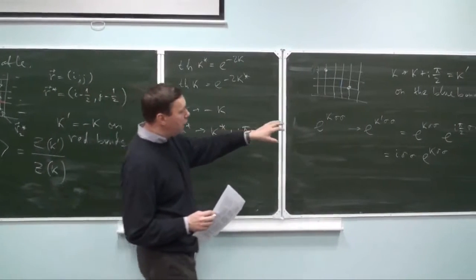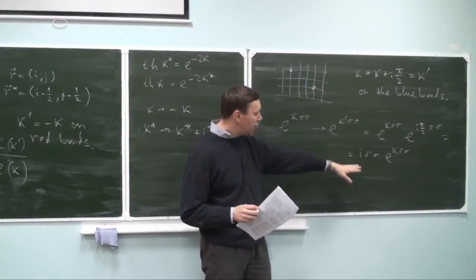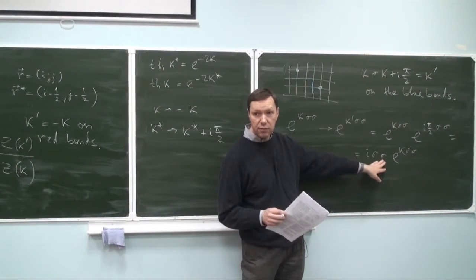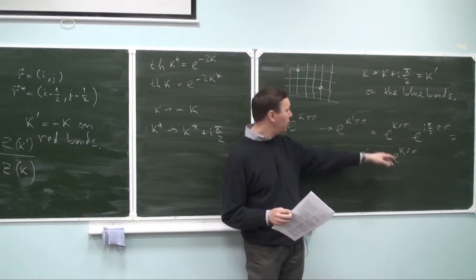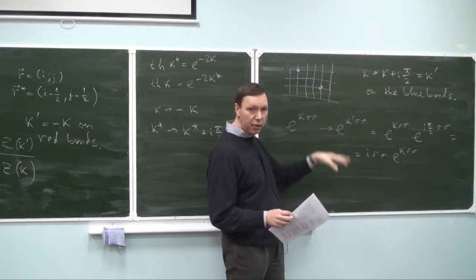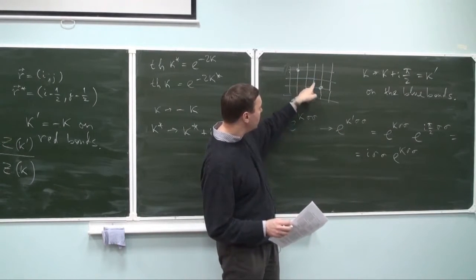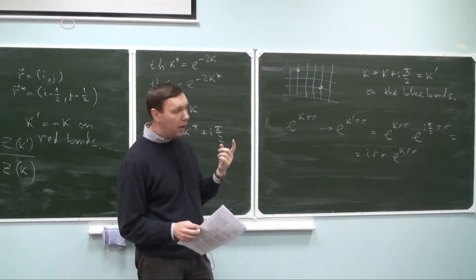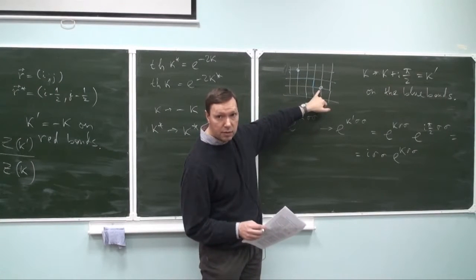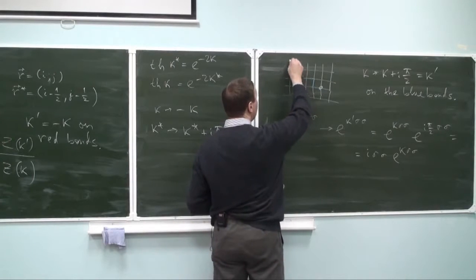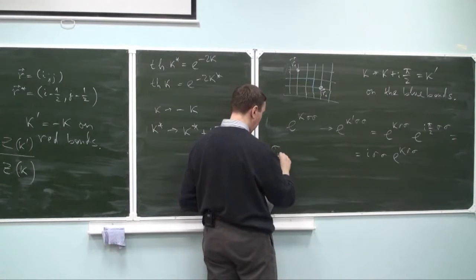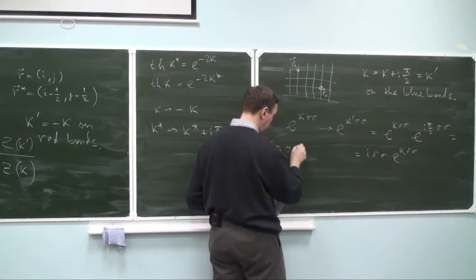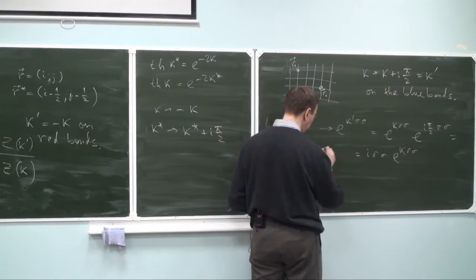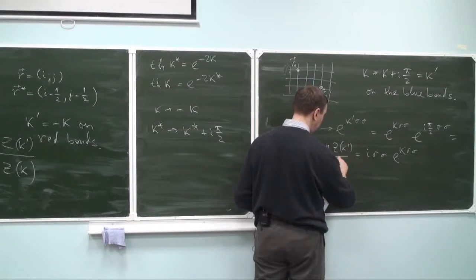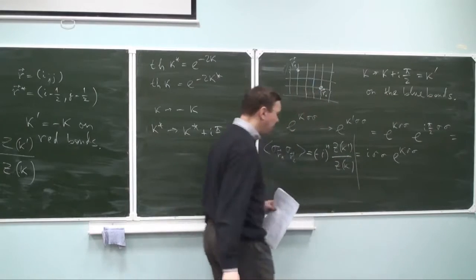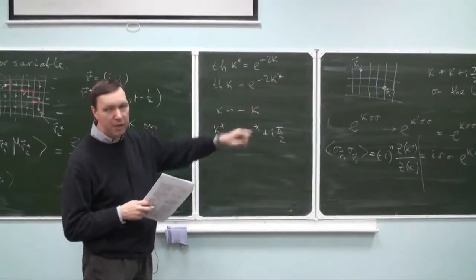And so, just modifying this bond strength brings down the product of two spins in front of the usual Boltzmann weight, right? Then you can do it along this path, and every time you pull down this product, the spins in the interior of this line will square to one, and the only things that will be left untouched are the original and final spins. So that proves that if this is R1 and this is R2, then the correlation of sigma R1 and sigma R2 is minus i to the n, times Z of K prime divided by Z of K, where n is the length of this path.